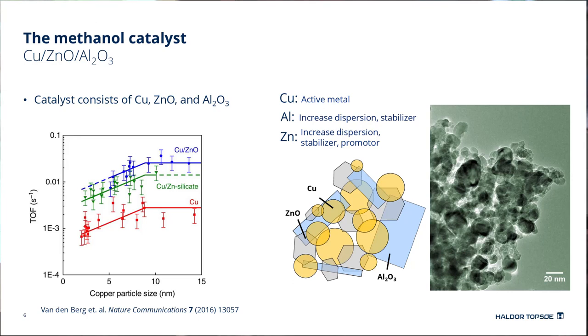The typical industrial methanol catalyst in the activated state consists of metallic copper, zinc oxide, and alumina. You add the copper to the system because it's generally seen as the active phase. It's on the surface of the copper particle that the chemistry is taking place. This is where the CO and CO2 are hydrogenated into methanol. So you want a nice, large, big area.